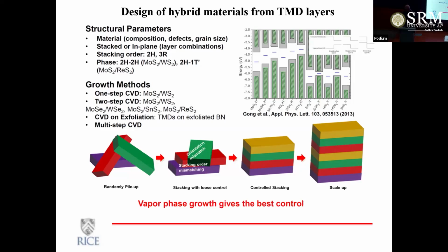So the picture that you're seeing here is precisely that, right? I'm able to make all these 2D atomically thin layers, and I'm going to put them together. I'm going to stack them, and so on and so forth. And of course, when you stack them, there are complications. It's not like shuffling two deck of cards, because now here we are talking about atomic lattices that you are aligning, right, when you stack. So first of all, there are different phases to these layers that you have to control. Secondly, you have the stacking problem, right, as I call it. Stacking problem is, again, the alignment between the two layers.